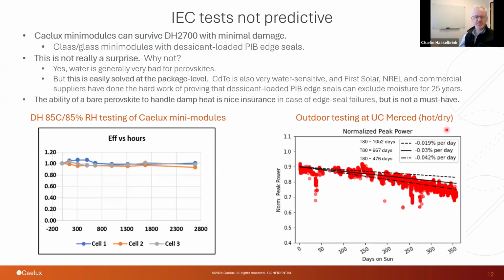That's fantastic. Want everyone to keep that up, of course, but our modules, I wouldn't argue that they last very long when they are exposed to humid environments. When we expose the bare perovskite devices with laser scribes on them to humid environments, they don't last so well. When we make them into glass mini modules with desiccant loaded PIB edge seals, they do great. So we've tested, I don't know why we stopped short of 3,000 hours just so we could say it, but you can see the result here. So we have basically no degradation, and that's because, of course, this is a package test.